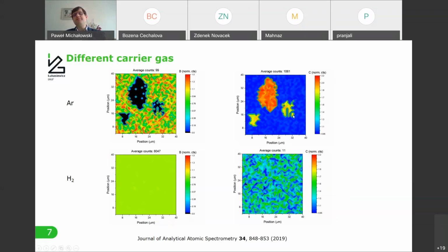So this means it can be estimated that there is about 10% of carbon within this sample grown in argon, whereas just traces, like in the ppm regime, of carbon for the sample grown in hydrogen. But what is quite interesting here is that we also see, in the same places where there is no boron or nitrogen, the carbon precipitates. And that gave us the idea that obviously this sample grown in hydrogen is of much higher quality and in general of much better applications. But these carbon precipitations are very nice markers to study the growth process again with SIMS.